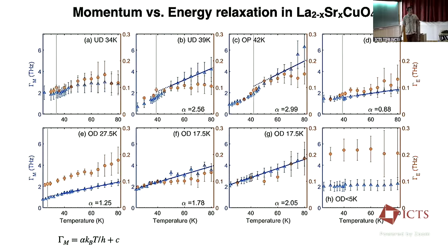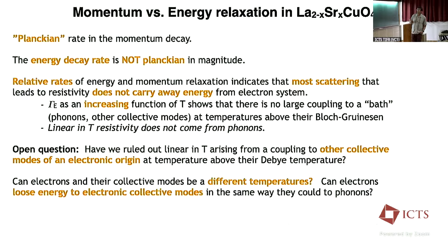So in all cases, the energy relaxation rate is an increasing function of temperature. That's important. Remember the old Phil Allen result: if I was in the elastic regime for phonon scattering, the energy relaxation rate would be a decreasing function of temperature. And in all cases, the energy relaxation rate is much, much smaller than the momentum relaxation rate. We can take a few things from this. One, in a regime where the momentum decay rate is, if you will, Planckian, the energy decay rate is not Planckian. The relative rates of the energy and momentum relaxation indicate that most scattering that leads to resistivity doesn't carry away energy from the electronic system. It doesn't mean that it's elastic scattering, but it could be electron-electron scattering, if you will.